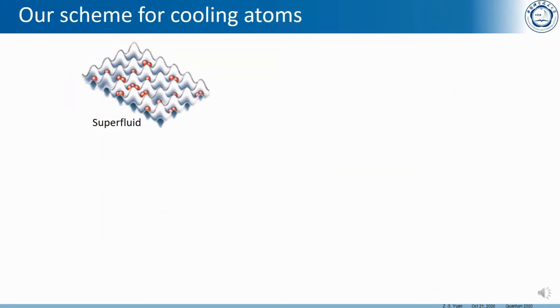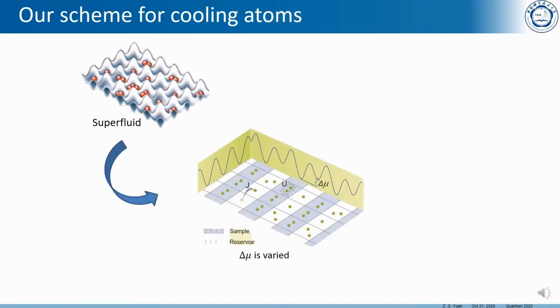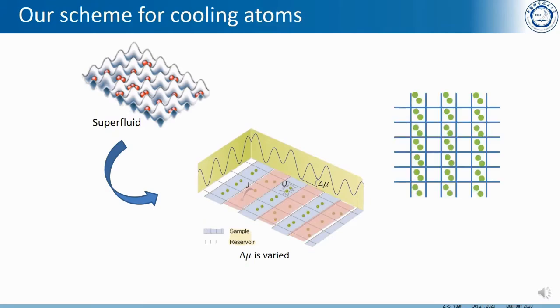In the experiment, we start from the superfluid state. We ramp up the lattice potentials, then the entropy will be redistributed among the samples and the reservoirs. Afterwards, we remove the reservoirs with higher entropy and leave the samples with very low entropy. We then redistribute the atoms into the whole lattice to achieve a system with unit filling.